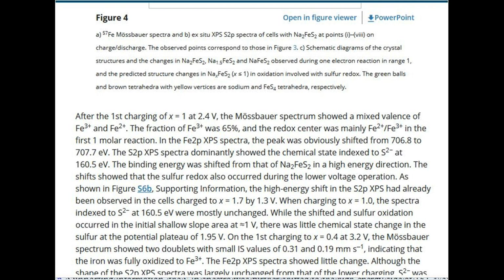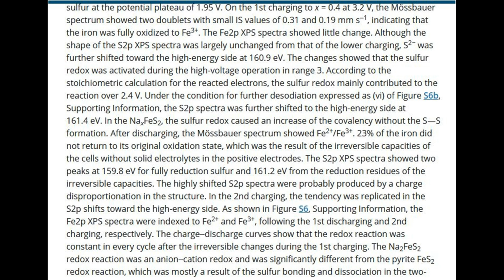On the first charging to x = 0.4 at 3.2 V, the Mossbauer spectrum showed two doublets with small IS values of 0.31 and 0.19 mm s-1, indicating that the iron was fully oxidized to Fe3+. The Fe2p XPS spectra showed little change. Although the shape of the S2p XPS spectra was largely unchanged from that of the lower charging, S2- was further shifted toward the high energy side at 160.9 eV. The changes showed that the sulfur redox was activated during the high voltage operation in range 3.